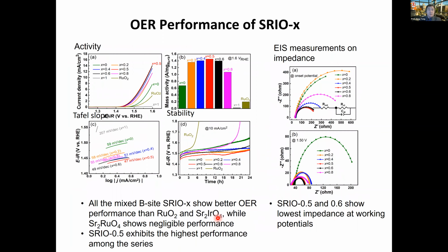So what we have observed, once again, is that right around the middle part of this, we start seeing the highest activities. Okay, so this is the one that we demonstrated in this particular series from 0 to 100%, dialing between the iridium and ruthenium system. And if you have them in between, we have the lower Tafel slope as well as the high activities. And all of these seem quite stable. If you do look at the stability study at 10 milliamps per square centimeter, it is so much better than the ruthenium oxide case.